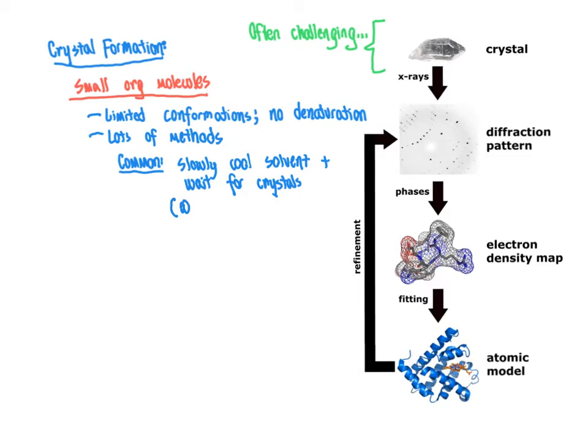This is done at a variety of concentrations and a variety of solvents, just to hedge your bets that one or more scenarios will work. Another approach is to carry out the crystallization in an open container, allowing slow evaporation of the solvent. Since the solvent is presumably organic and volatile whereas the compound of interest is not, as the solvent evaporates slowly, the compound becomes more concentrated. If you're lucky, it will slowly come out of solution as a crystal with a recurrent crystalline pattern. If not, it will come out as an amorphous material, from which you absolutely cannot collect adequate x-ray crystallography data.